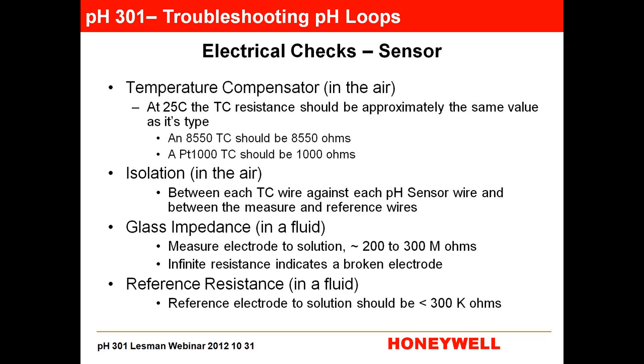Reference resistance, you can check that. Again, you just put the lead on the reference electrode wire and then drop it in the solution. That reference should be less than about 300 K ohms. Anything above that tells me that your reference is getting poisoned or compromised in some way. And so we'd have to take a look deeper to see if we could figure out what the issue is.